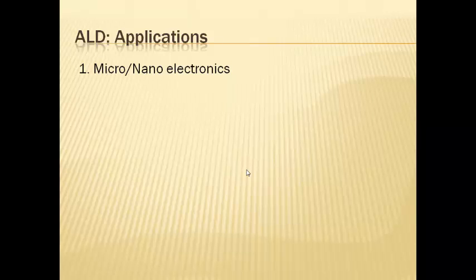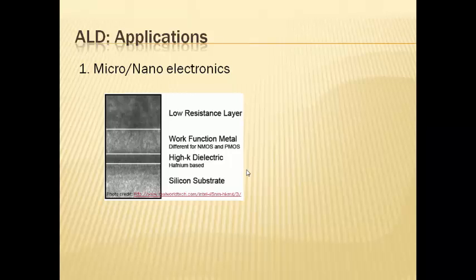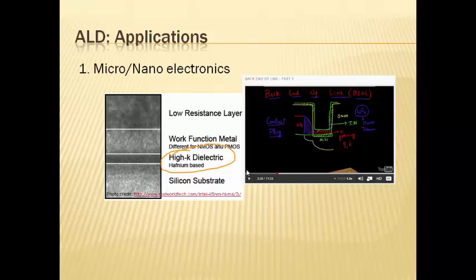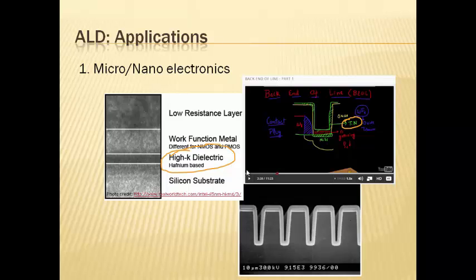We will now look at a few of the important and innovative applications of ALD. Common but certainly important applications include those in micro and nanoelectronics, such as deposition of high permittivity dielectrics to reduce the gating effect for 45 nanometer node transistors. Other applications include transition metal nitrides like titanium nitride or tantalum nitride as diffusion barriers, as has also been covered in the course. Magnetic recording heads are some of the newer applications, while how ALD may be applied in DRAM capacitors has already been discussed before.